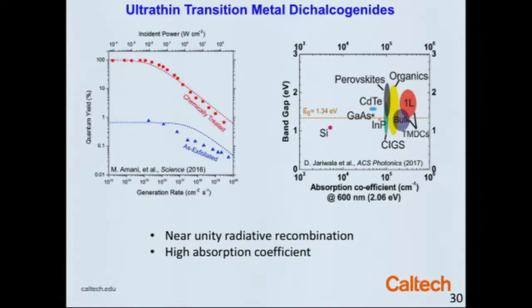A very exciting development that came from the lab of Ali Javey about a year and a half ago was the recognition that by chemical functionalization of the few defects on the basal plane of molybdenum disulfide, we could make the luminescence quantum yield close to 100%. This is as luminescent as gallium arsenide or perovskites. This is a shocking development.